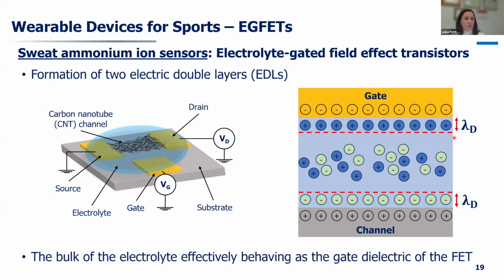The distance, the so-called Debye length, is very small, and that means that we have a really large capacitance, both at the electrolyte gate interface and at the electrolyte channel interface. And in that way, what happens with this rearrangement is that the bulk of the electrolyte behaves as if it were the gate dielectric of the field effect transistor. So that's a little bit the structure.